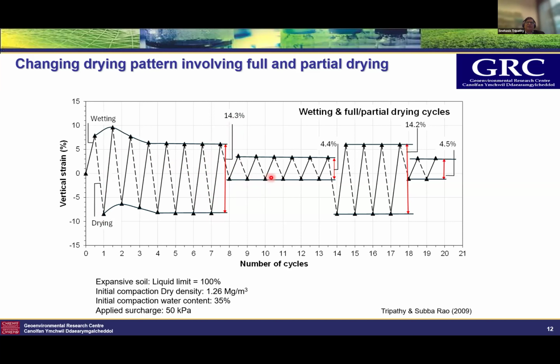Then the drying pattern was changed to a partial drying pattern. The soil exhibited equilibrium swelling and shrinkage strains immediately. The full and partial drying patterns were then repeated in the next two stages. The results again show that if a soil has experienced a severe drying pattern in the past and has attained an equilibrium, a lesser drying would result in an immediate equilibrium state being reached. What these results show is that it would be prudent to test soils alone or soils along with other components to explore how they would respond to climate change.